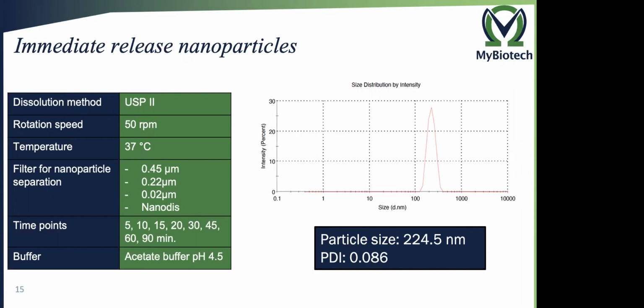We have done the dissolution for 90 minutes. And as I told before, we have used the acetate buffer pH 4.5. On the right side, you can see the particles that we prepared for that. The particles were around 225 nanometers, again with a low PDI of 0.086, which shows, again, the homogeneity of the particles.